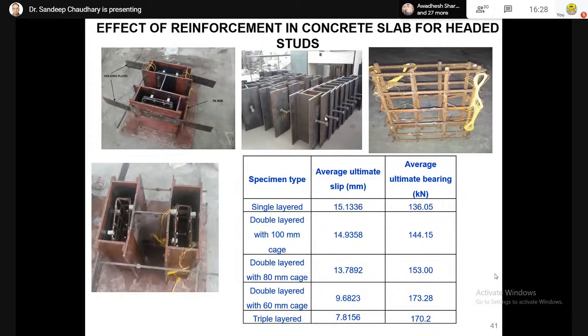So different types of reinforcement patterns were used in the concrete slabs. There's a single layered, double layered with 100 mm cage, double layered with 80 mm cage, 60 mm cage, even triple layered reinforcement cages. And you can see here that the ultimate slip is changing. If you're moving from single layered case where the ultimate slip is up to 15 mm, in triple layered case, the ultimate slip is only 7.8 mm. So there's a huge difference between the single layered and triple layered. And similarly, the average ultimate bearing load, what we could see in single layered was 136 kilonewton. That load carrying capacity increased from 136 kilonewton to 170 kilonewton.